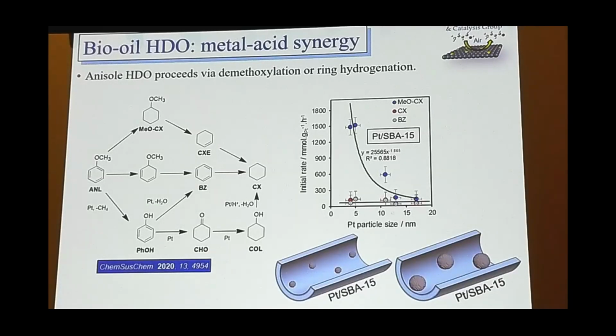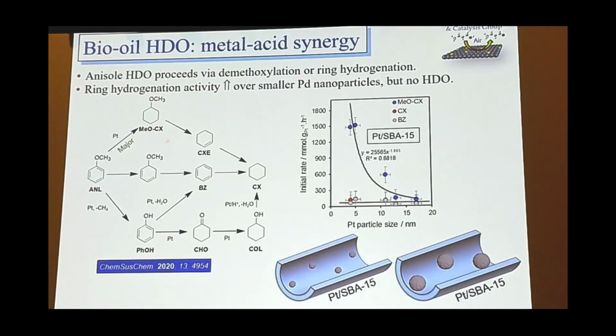So if you look at the hydrogenation of anisole over platinum SBA-15, we vary the platinum particle size, you can see that smaller particles give you much higher rates. So in this case, what we have though, in the catalyst that stops at this point here, you make very little of the deoxygenated product. So the pathways taking you through to deoxygenation, so that's hydrogenolysis or direct demethylation, are very slow and are minor pathways. The main reaction is ring hydrogenation, and it just gets stopped at the alkyl ether.